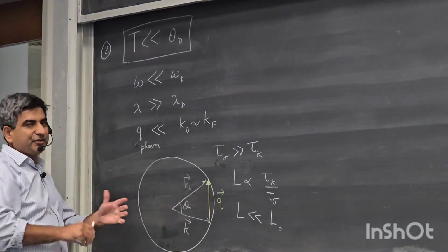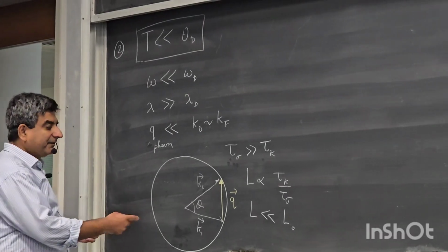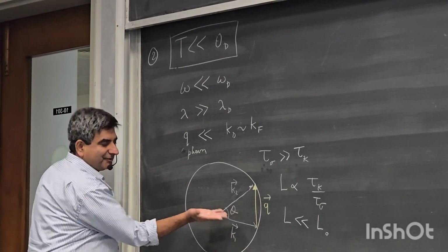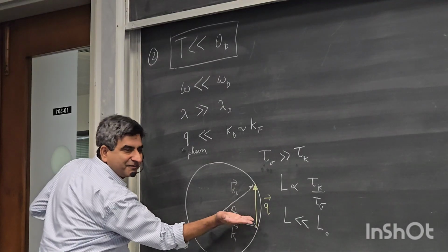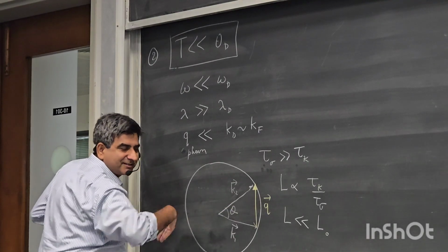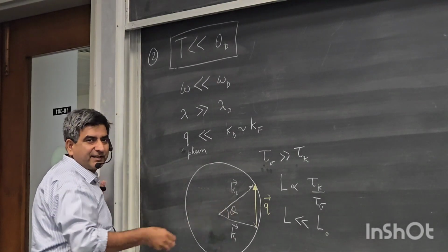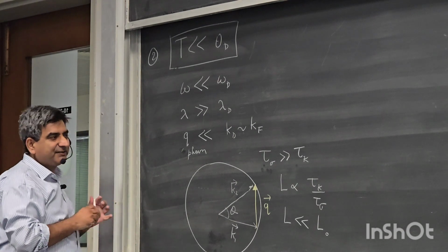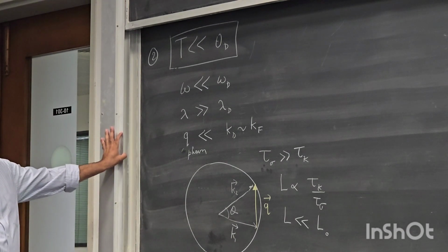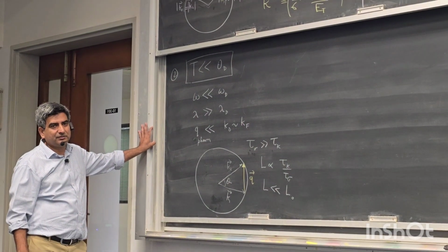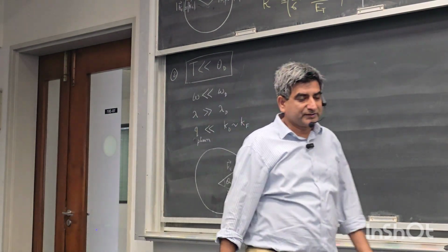So the efficiency of this process, really for an efficient process you want theta to be 180 degrees so that you can get a transition from this side of the Fermi sphere to the other side. But now this theta is much less than 180 degrees. So there is an efficiency compromise on this scattering process, and we can calculate this efficiency compromise.